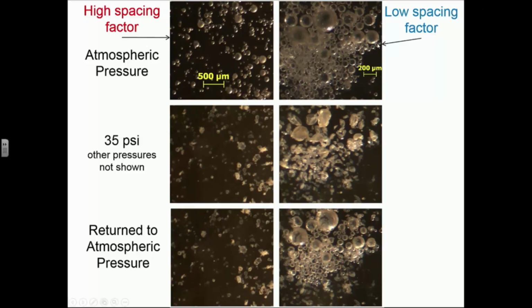Now let's look at the low spacing factor. Look at these bubbles, closely spaced bubbles. As you increase the pressure, some bubbles dissolve, but a lot of them don't. But when I decrease the pressure, a large number of the bubbles stick around.